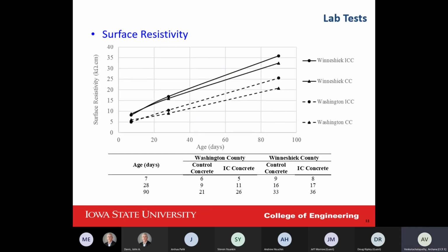And another thing which is important, well, everywhere, but also in Iowa, is that when it snows, they use a lot of salt on the concrete. So the less penetration happens in the concrete, the less chloride gets to the bars and destroys the concrete. So higher resistivity means higher life expectancy for the road pavement. As we can see, using the internal curing method increases the surface resistivity, which is directly related to life expectancy and lower maintenance.